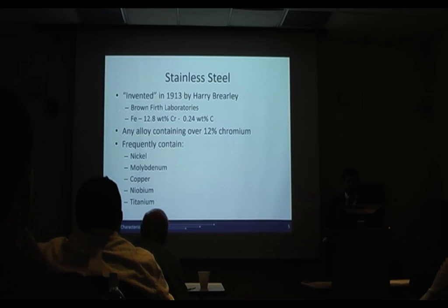This was first done in about 1913 by Harry Brearley at Brown Firth Labs, and he noticed that the samples he had added chrome to when he was making knife steel had significantly resisted etching, and the composition that this happened with was 12.8% chromium and 0.24 weight percent carbon. But what they found afterwards is that any alloy containing over about 12% chromium resists corrosion quite well, and also frequently added are nickel, molybdenum, copper, niobium, and titanium.